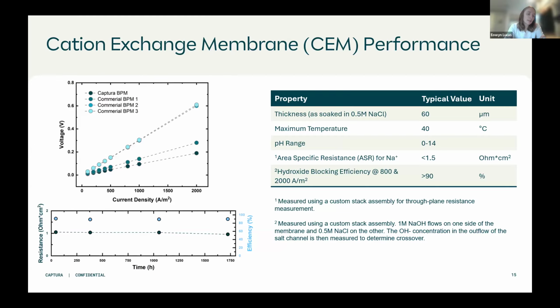For the stability in these cases, we typically do stability measurements by soaking the membrane for extended periods of time in whatever solution condition and temperature it will see, and then taking repeated measurements of the resistance and the blocking efficiency. And again, here this test ran for over 1,500 hours and remained stable in the efficiency and the resistance as well. And similarly, we do additional measurements, thickness, temperature, all of that good stuff.